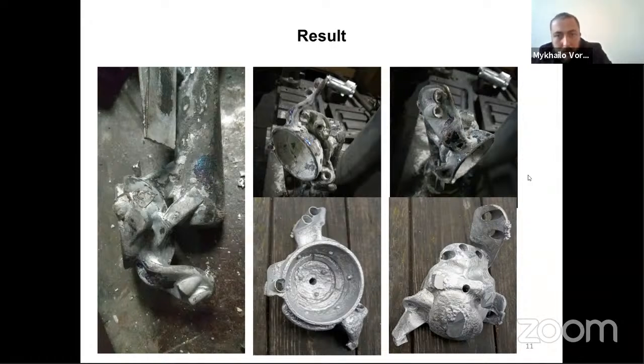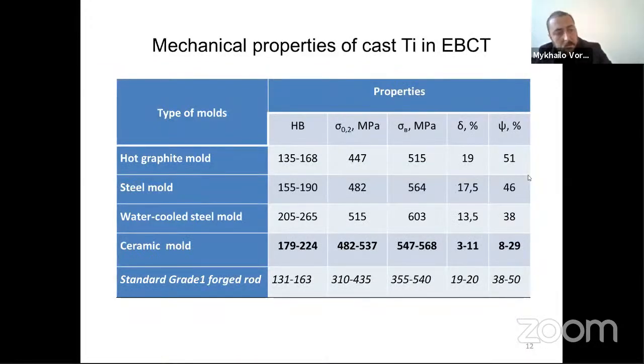We can see even the prints of PLA fiber that were left from our model. We also compared mechanical properties of our metal with similar examples obtained under other conditions. Here you may see them, and electron beam casting technology, as we can see, allows us to produce castings with relatively high properties. Sometimes they are even close to deformed metal. As for us, the properties of our casting are more than sufficient for producing prostheses and some kinds of implants.